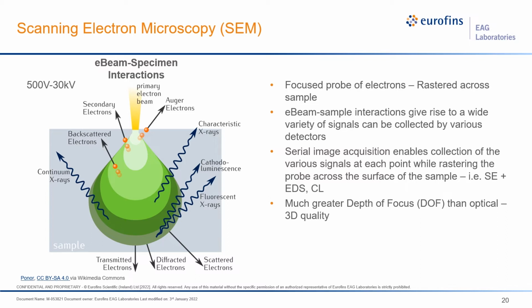Secondary electrons are typically utilized to give topographical information about the sample, but at the same time, we can collect electron beam induced current signal and then correspond that to the secondary electron image. So we have a good fiducial reference for that. Or we can collect X-rays or Auger electrons or backscatter electrons, etc.